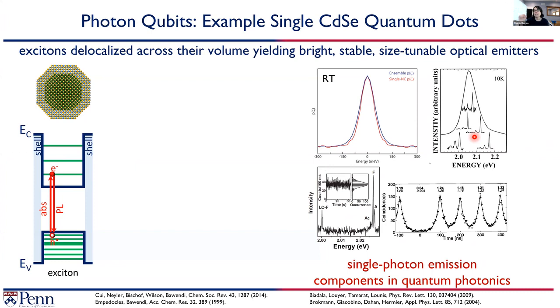Then there were some even nicer, higher resolution spectroscopy done where you can see this same progression as well as some of the acoustic phonons. And key to thinking about these as platforms and the excitons were measurements of correlation, what's known as anti-bunching, where you can see that at zero time scale, you don't have the coincidence of two photons. And this is a characteristic signature that is looked for in characterizing single photon emitters. So these colloidal quantum dots really can be used as single photon emitters.